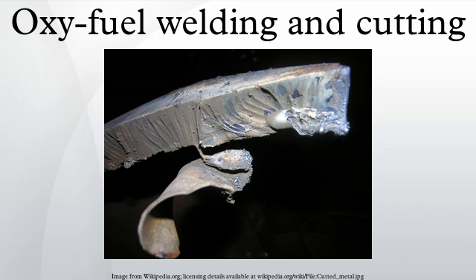It is worth noting several things at this point. The oxygen flow rate is critical. Too little will make a slow ragged cut, while too much will waste oxygen and produce a wide concave cut. Oxygen lances and other custom-made torches do not have a separate pressure control for the cutting oxygen, so the cutting oxygen pressure must be controlled using the oxygen regulator. The oxygen cutting pressure should match the cutting tip oxygen orifice. Consult the tip manufacturer's equipment data for the proper cutting oxygen pressures for the specific cutting tip.